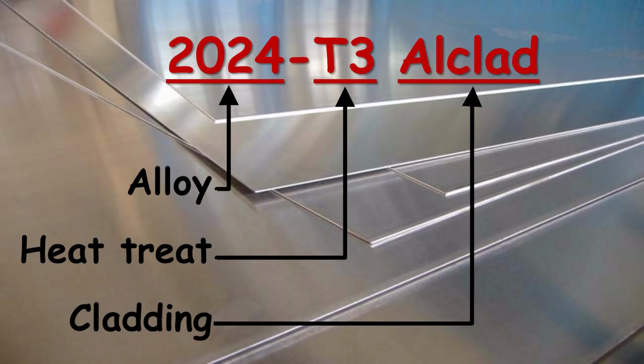We're about to talk a little bit about heat treating, but heat treating is a process that's used to change the characteristics of the metal a little bit, and we'll talk about that in just a moment. And then the alclad means that the metal is, after it has been formed and heat treated, the exterior is plated with a very, very thin layer of pure aluminum. Typically 2024 T3 alclad sheet metal, which tends to be 20 thousandths, 32 thousandths, 40 thousandths thick, has a coating of pure aluminum on both sides that's about 1,000th of an inch thick.